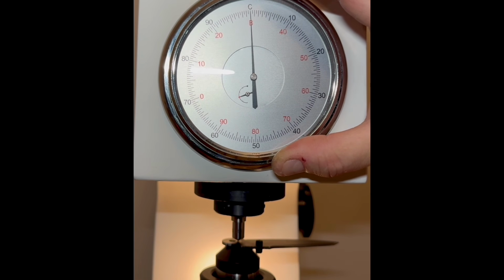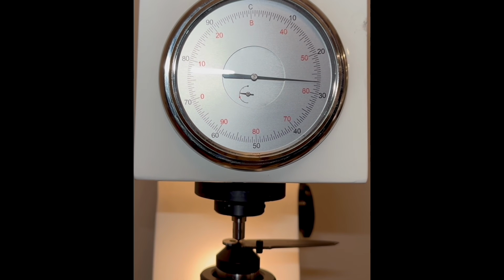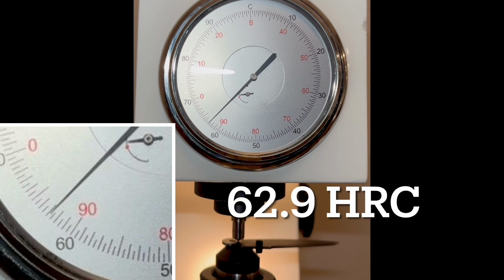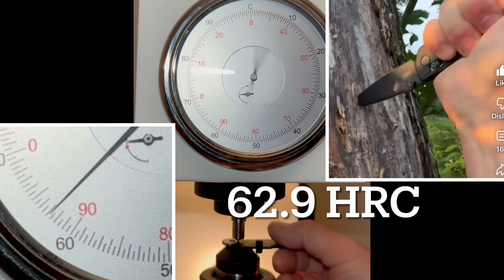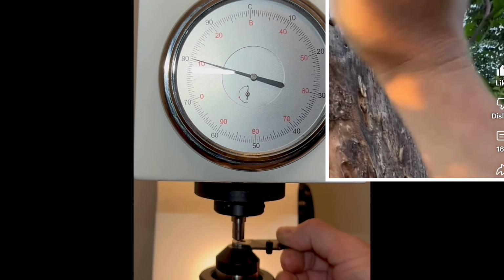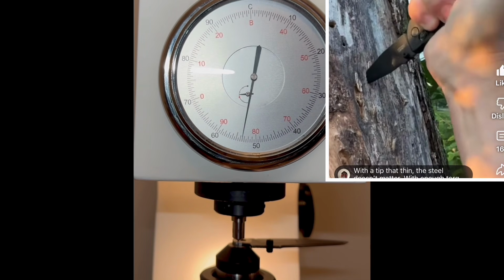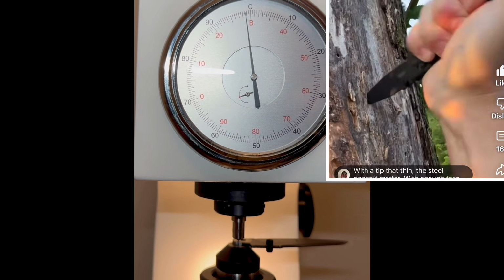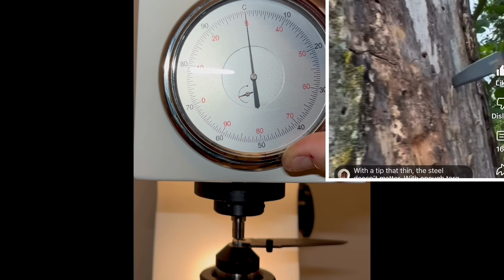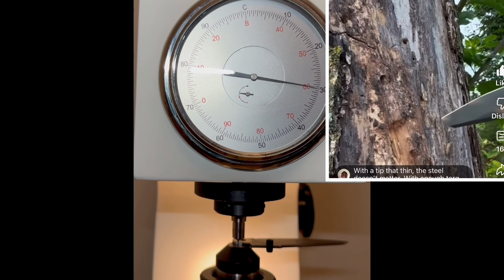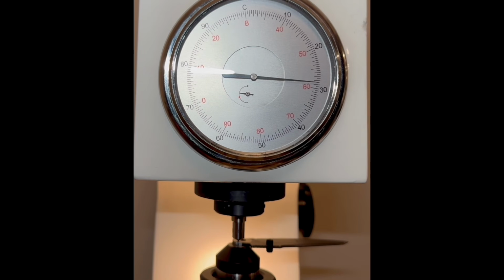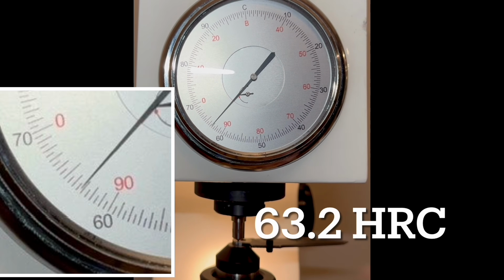So this blade, I don't know if you noticed, has a reshaped tip. I'll explain why after we check the result, which is coming up at 62.9 HRC. I used to do what I called Tree of Doom stabbing tests, where I stab the blade into the Tree of Doom 25 times to see if it will break the tip off. And this one fell victim to the test. And so I knew that the hardness on this blade would be pretty high. This time I got 63.2 HRC.